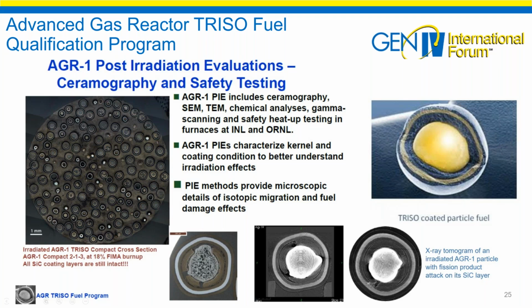For instance, this is one of the particles in this pizza pie over here. That's what I call it. This is a slice across a compact, and you'll see that there are different sizes here because you're entering different particles at different heights through it. And what's important is that this white area is the silicon carbide layer.